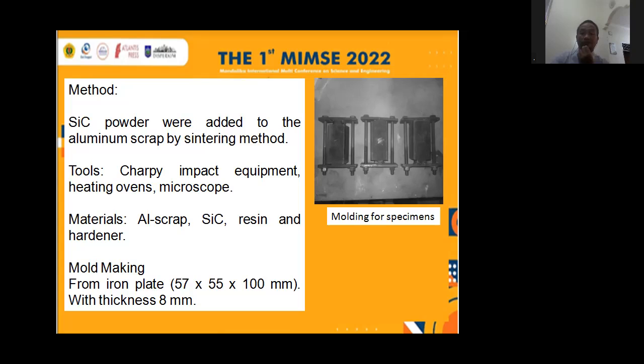There are three molds that we used in this study. They are 3 square molds of the same size, with dimensions 57 millimeter by 55 millimeter by 100 millimeter. The mold material is an iron plate with a thickness of 8 millimeter for the pressing, and 3 millimeter for the wall of the mold.